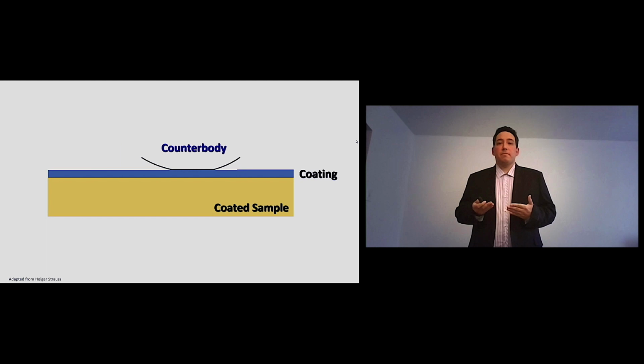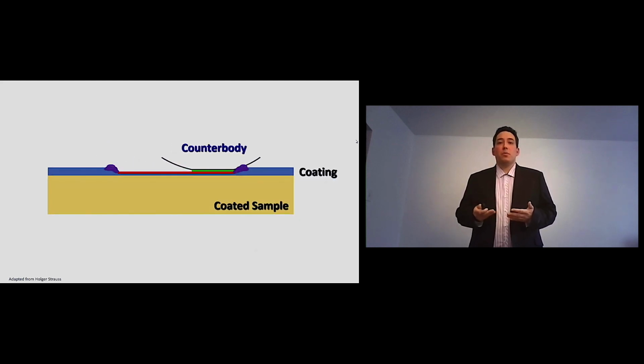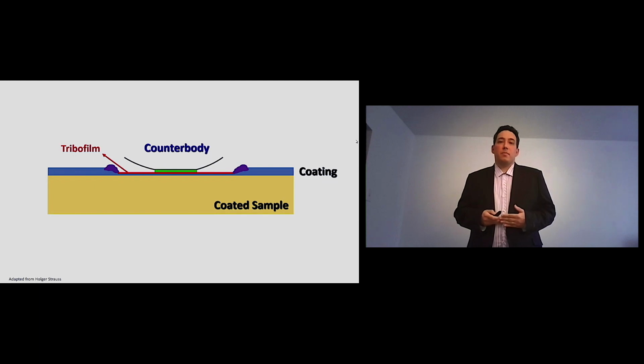Well, now, if you put that into motion, what you would see is that different things can happen at the surface. Material can get mixed and oxidized and form what we call a tribofilm. Material can also get detached from the surface and attached to the counterbody or counterface, forming what we call a transfer film. And material can leave the wear zone, what we call wear debris.